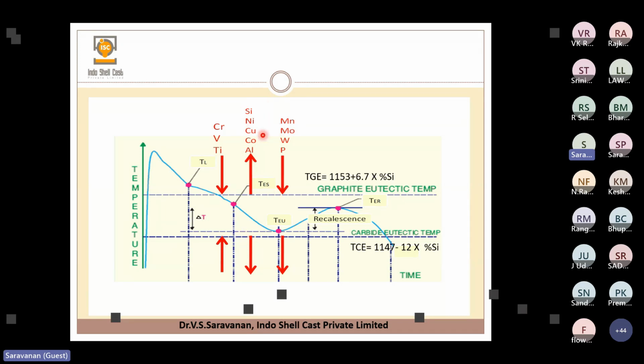And silicon, nickel, copper, cobalt, aluminum widen the range. It is good, because if it is widened, then automatically TEU will come inside. So they are saying it is good. Some elements push both lines simultaneously: manganese, moly, tungsten, phosphorus. That is also not good. So the first not good is chromium, vanadium, titanium, the second not good is this, and this is good. According to that, these elements push these boundaries, and the solidification potential varies according to the elements present.